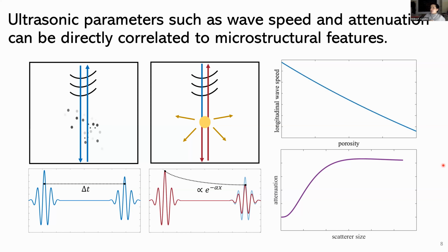The ones that I'm going to show you today are in the first round of characterization that we can do, and that is wave speed and attenuation. Just as a crash course, we know that wave speed is related to the effective properties of the medium that the wave is propagating in. So in our case, we're going to relate wave speed to something like porosity. We know that there is an inverse relationship between these two parameters.